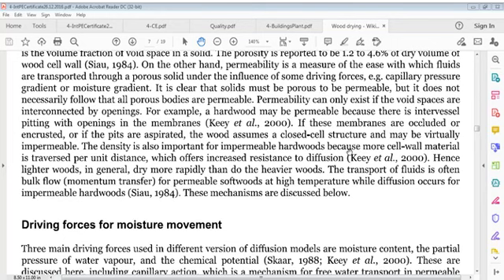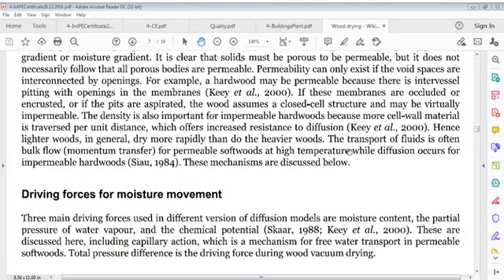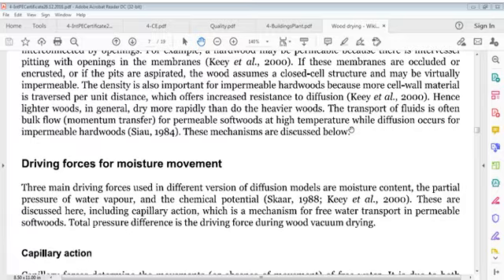If these membranes are occluded or encrusted, or if pits are aspirated, the wood would assume a closed cell structure and may be virtually impermeable. Density is also important for impermeable hardwoods because more cell wall material is traversed per unit distance, which offers increased resistance to diffusion. Hence, lighter woods in general dry more rapidly than do heavier ones. Transport of fluids is often bulk flow, momentum transfer, for permeable softwoods at high temperature, while diffusion occurs for impermeable hardwoods. These mechanisms are discussed below.